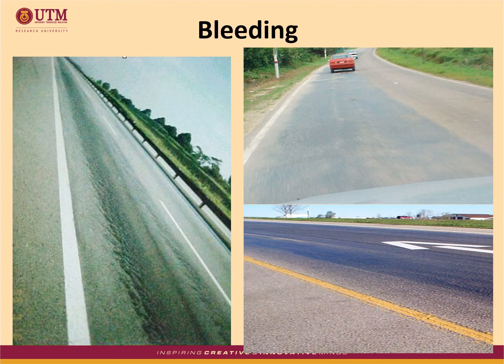Okay, another type of surface defect is the bleeding phenomenon, which refers to a thin layer of bitumen appearing on the pavement surface. This thin layer of bitumen will reduce the texture depth and also the skid resistance of the pavement, especially under wet conditions. Bleeding can occur as a result of excessive bitumen in the asphalt due to a poor mix design or manufacturing problem. For treatment, in the case of minor bleeding, coarse sand can be used to blot up the excess bitumen. For major bleeding, it can be corrected by cutting off the excess bitumen or by resurfacing.